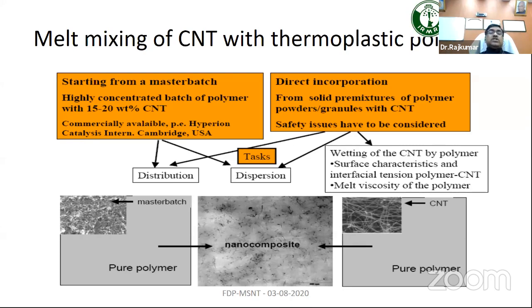Maybe the dispersion is good in a smaller batch, but distribution is not happening at the larger level, because within the residence period of 10 or 20 minutes of mixing, it's not happening basically. So this is really a challenge for mixing of such things. And with direct incorporation, again the same thing: the surface chemistry and interfacial tension, all such chemistry